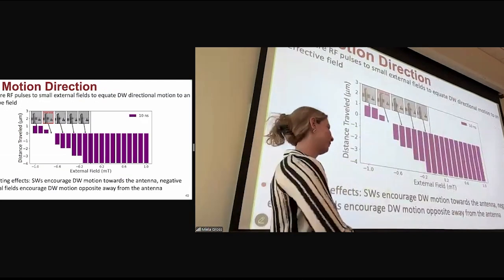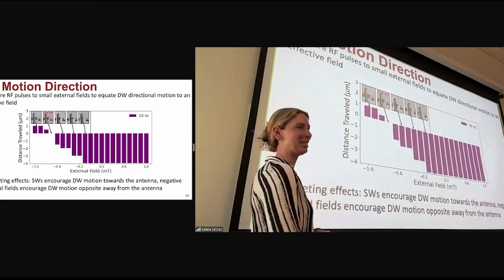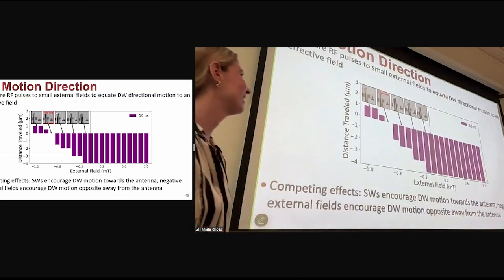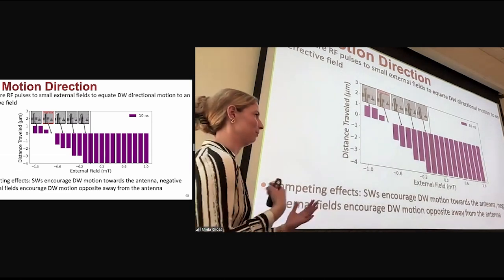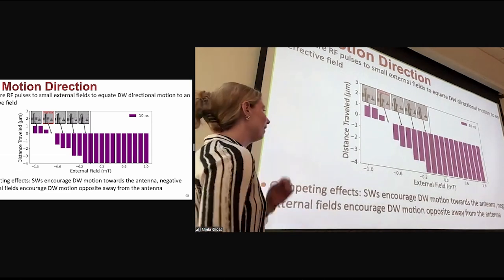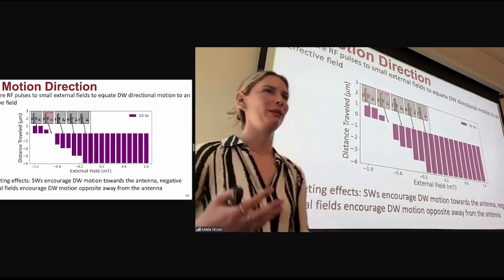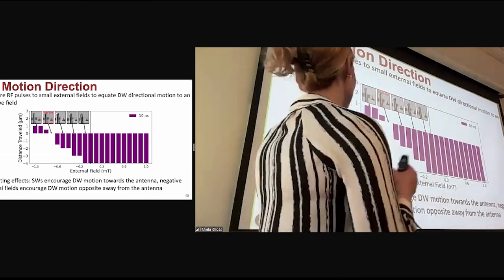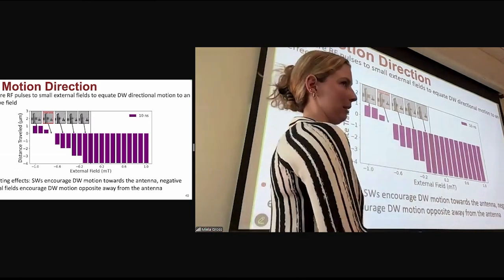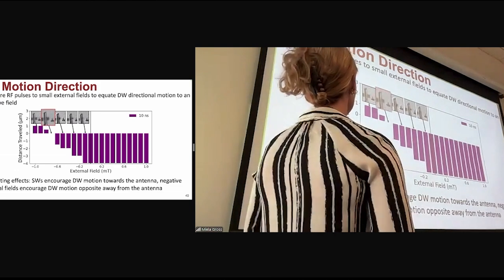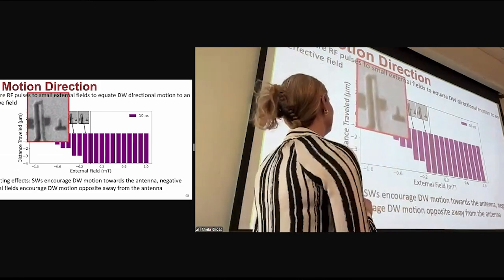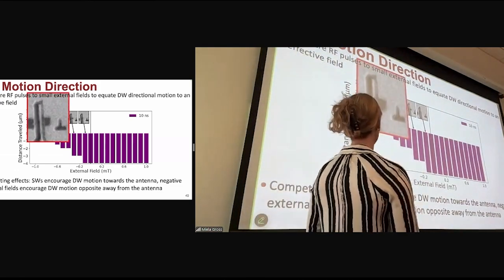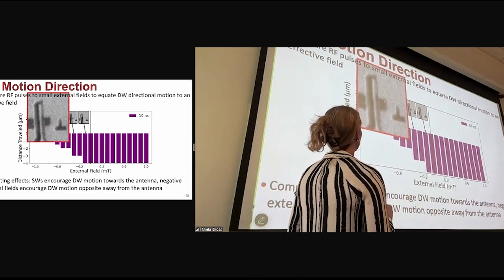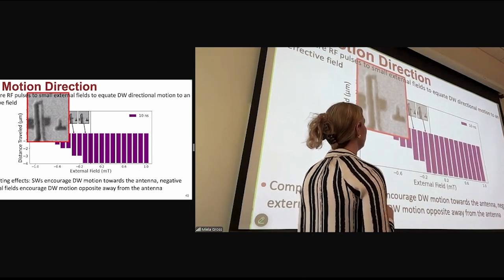So now this is the fun part. This is the part that I'm very excited about, which was looking at the directionality of our domain wall motion. And the way we set up this experiment was to have competing effects between spin waves and external fields. So we start with this initial state here, and there's a down state, as you can see, around this injector antenna. And that means we have this little domain wall about 4 microns to the right of this injector antenna.